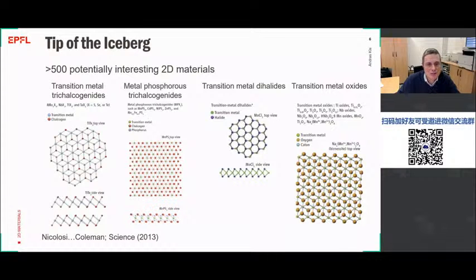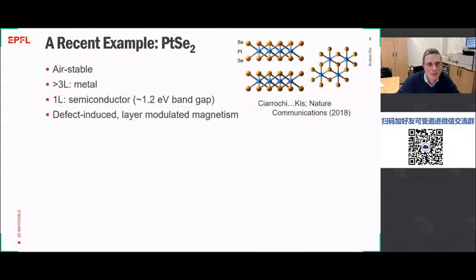One recent example of such wide tunability is a work that also came from my group. One material that we looked at recently is platinum selenide, which has this kind of structure, and it covers a very broad range of tuning properties, because in bulk form it is a semi-metal or a metal. Once you thin it down to a single layer, it becomes a semiconductor. So it has a broad range of electrical tunability.